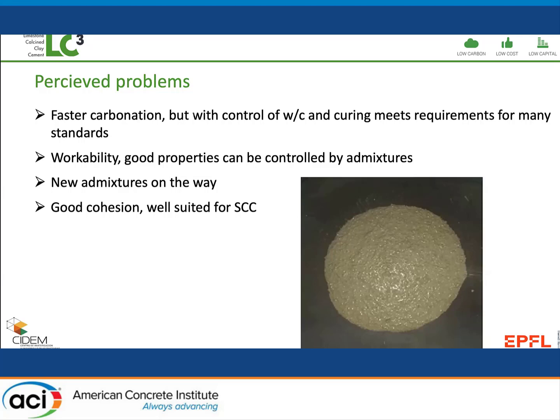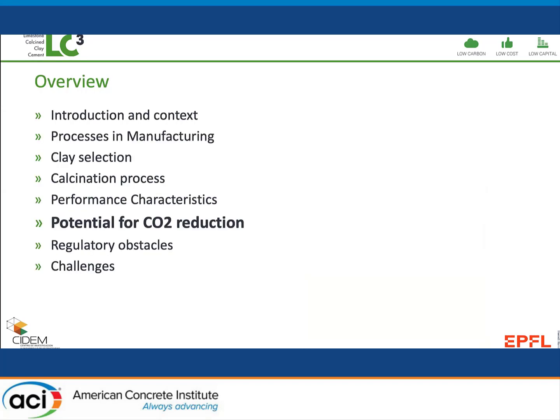Carbonation is faster, but as Jesper said, it's very much in the same range as what you get with existing SCMs like fly ash and slag. So the potential for CO2 reduction, of course, the potential on the level of the actual cement depends on the conditions of calcination, the proximity of the clay. We've shown that it can be up to 40%.